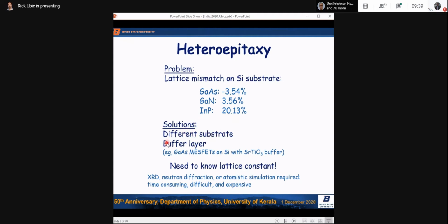So the other thing you can do is to use a buffer layer, something with a lattice constant between silicon and the semiconductor you want to use, and that will help take up some of the strain without causing a lot of threading dislocations. If you want to do this, though, you need to know the lattice constant of the buffer you're using, or of the semiconductor you want to use, right?